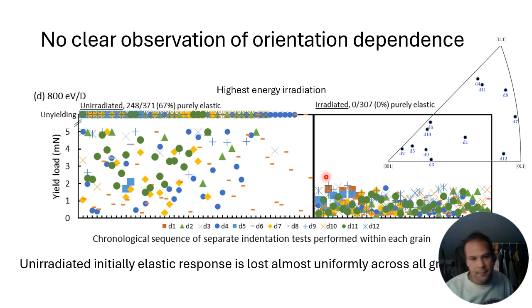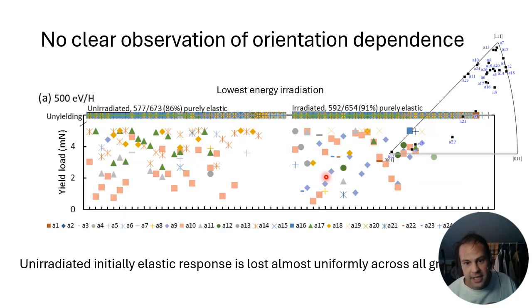So I thought, okay, what happens if we do a low energy that we really strongly expect to be below the threshold displacement energy? With 500 electron volt protons, there's basically no observed difference between the unirradiated and the irradiated grains. Almost all of them are purely elastic before irradiation, and after irradiation, still almost all of them are purely elastic. So it really seems like this 500 electron volts is, as we had previously expected, below this damage threshold, or at least we're not seeing any effect of this irradiation condition in our nanoindentation experiment.